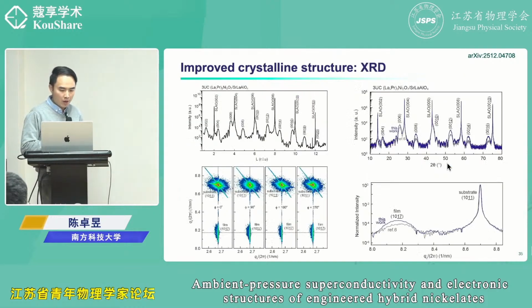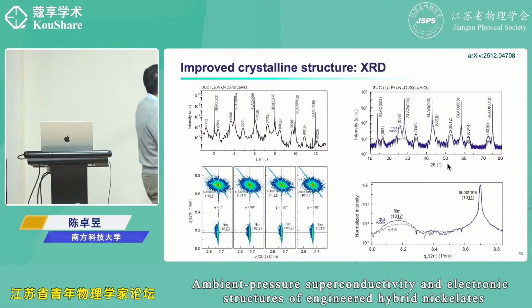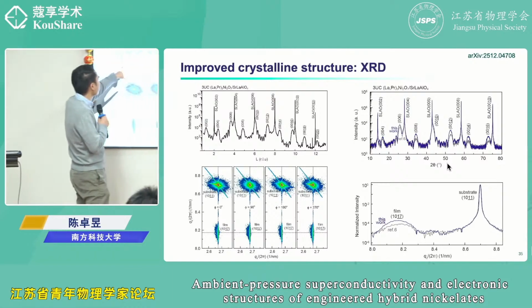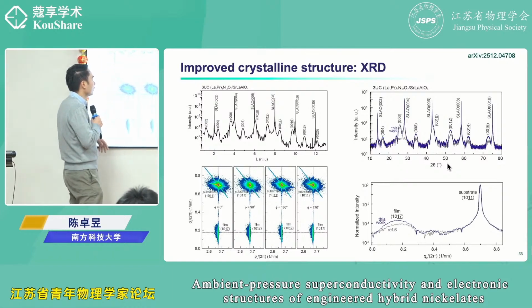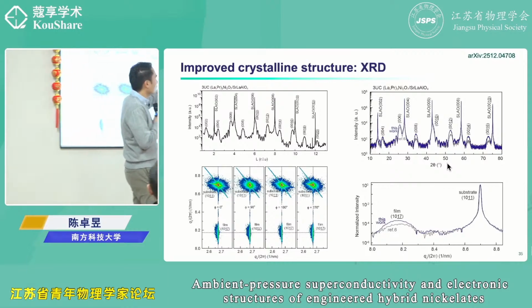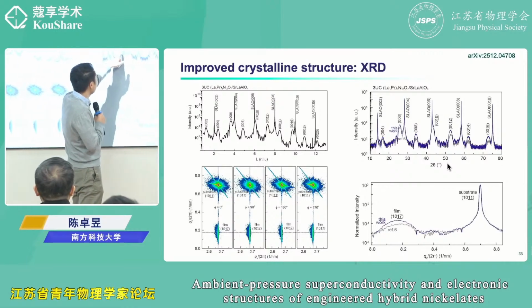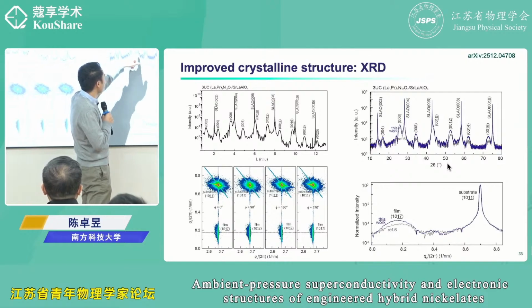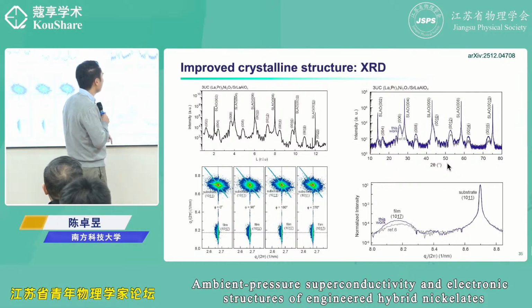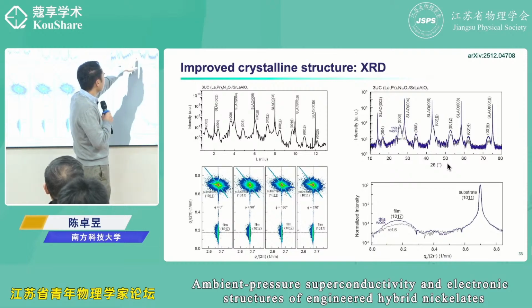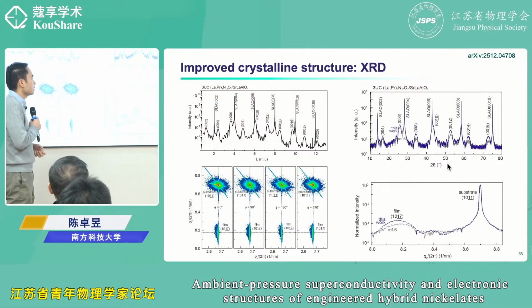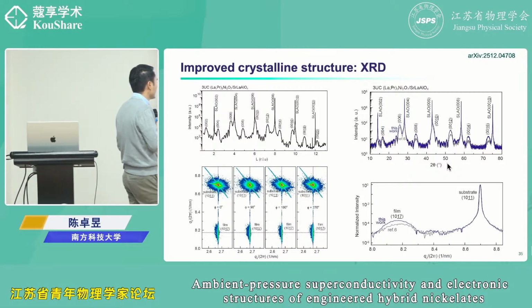And using X-ray diffraction, it is also quite obvious that our crystalline structure is greatly improved. This is a synchrotron X-ray diffraction. You can see this oscillation is oscillating all along. And this is the comparison with this reference 6, our original report, the first Nature paper report. So you can see that it has a pretty obvious enhancement of these X-ray diffraction peaks.